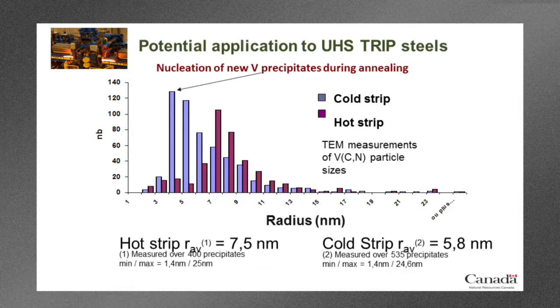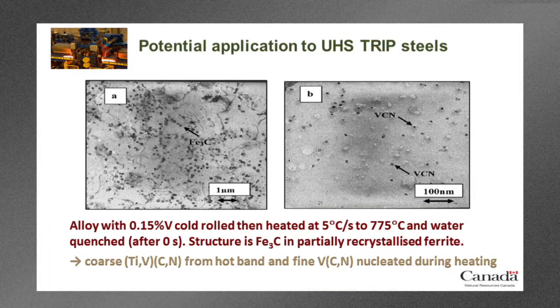So there's only one possible conclusion for that. These extra precipitates that come in the cold strip are new ones. They're not growth or coarsening of the existing precipitates from the hot strip. Now, we did some more TEM work on that, and here's a few images to show you.